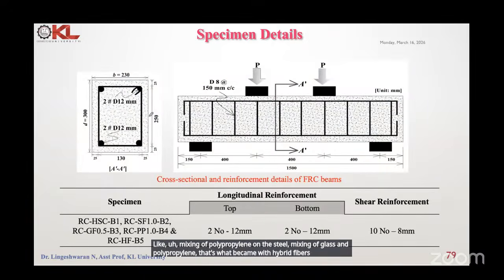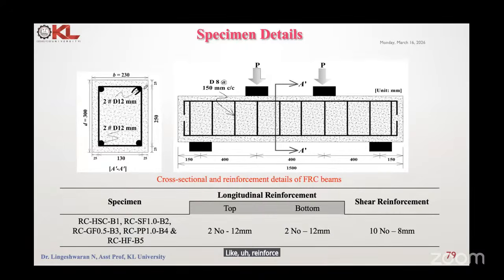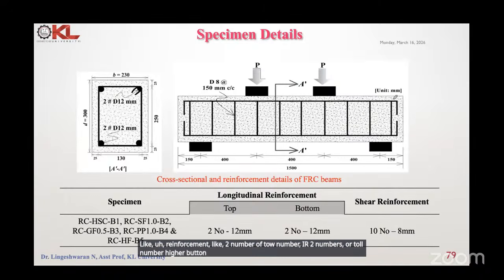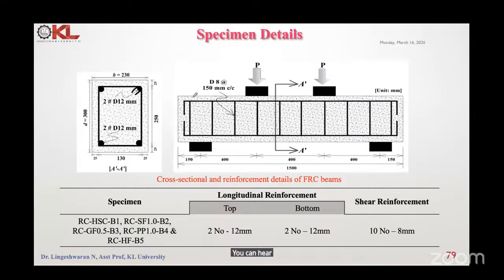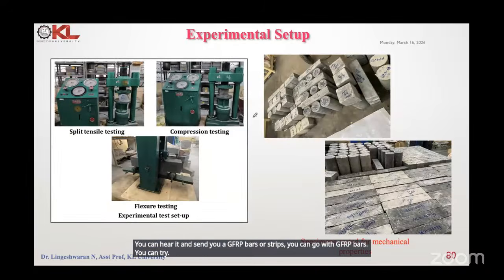You can see here the specimen details we followed, like reinforcement of 2 numbers of 12 mm diameter bars at the top and 2 numbers of 12 mm diameter at the bottom. These are the normal conventional methods, like how we do the structural design in RCC. So like that we did. Even if you are going with hybrid fiber, you can change your stirrups to GFRP bars. You can try it as an attempt, and if you get a good result, you can make it a patent, and you can make it a publication to create awareness among researchers and clients.